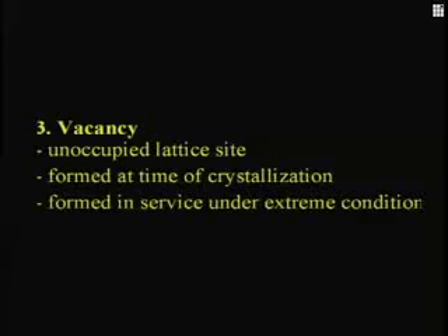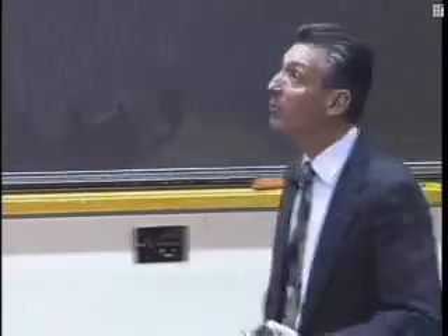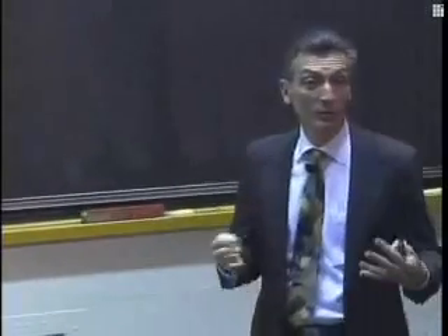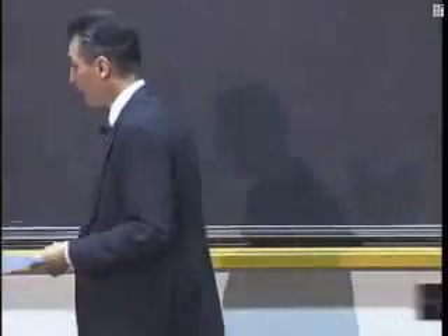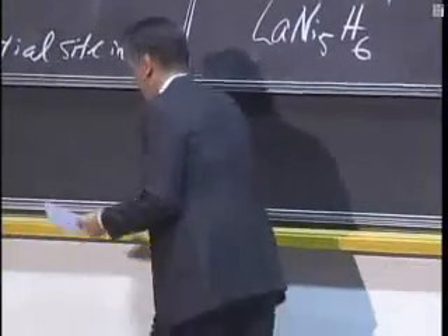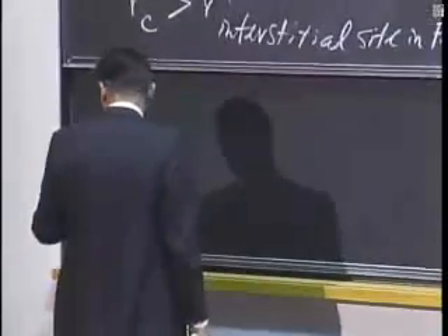And then there's an extreme case, such as the wall of a nuclear reactor vessel, where under high bombardment of neutron flux over time, atoms are literally dislodged from their lattice positions. And you put this on a regular maintenance schedule because, as you can imagine, over a certain period of time, the material starts to look at the atomic level more nearly like Swiss cheese, and so that's not good. So vacancies are present, and they're always going to be present.